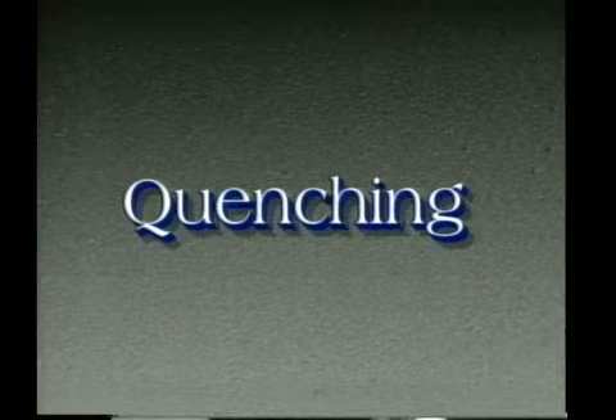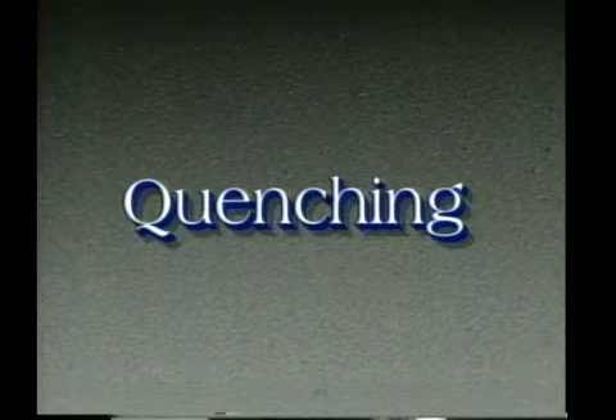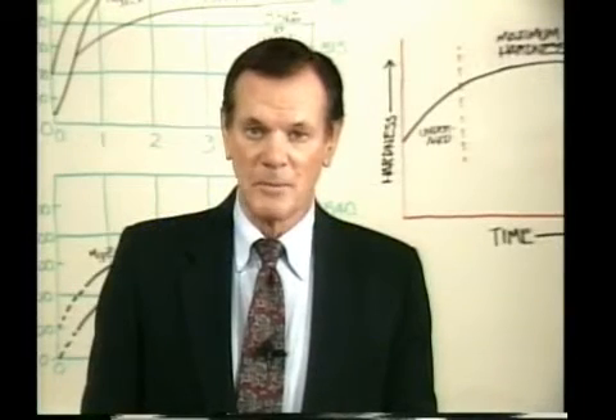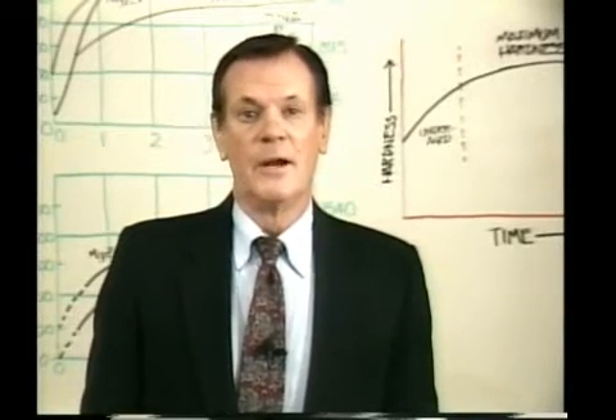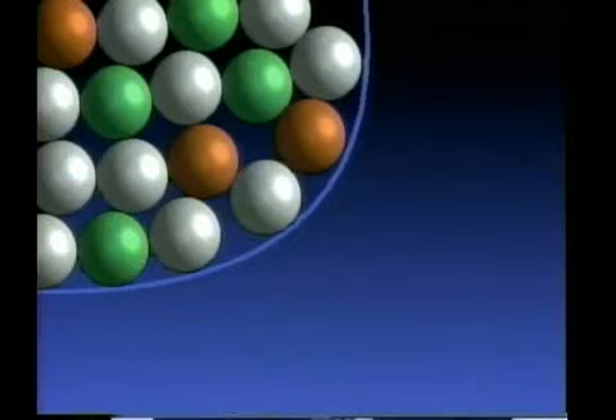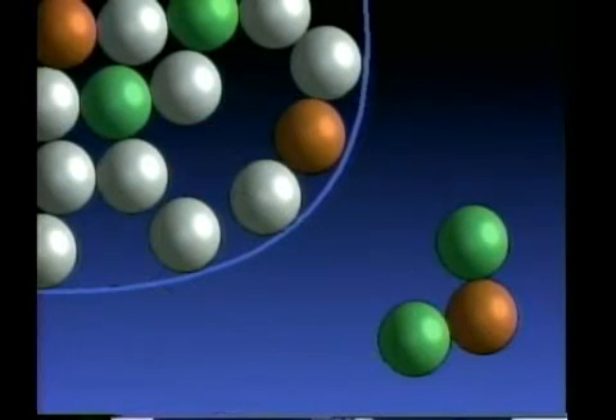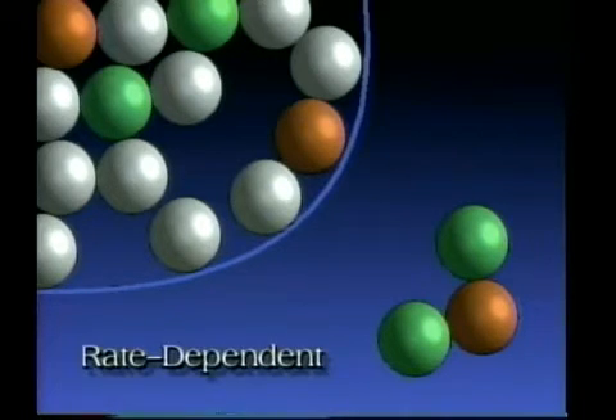As we have observed in the previous discussion, at the solution heat treating temperature, the alloying elements are dissolved in the aluminum lattice, while at room temperature, they are located at grain boundaries or other large defect areas of the structure. If a part is slow cooled to room temperature from solution treating temperature, the atoms move within the lattice from their original dissolved location and congregate at defect locations, particularly near the grain boundaries, large voids or undissolved particles, where they will not have the opportunity of achieving a hardening effect. The atom moving process is a rate-dependent process in that it takes a specific amount of time to occur.